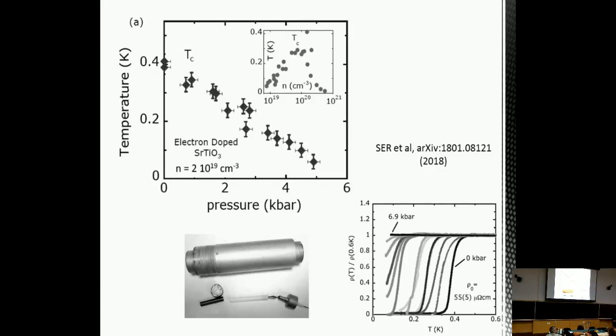And we measured the pressure dependence of superconductivity in strontium titanate. So here's the resistivity versus temperature at different pressures. And you can see here the red curve shows that superconductivity is rapidly destroyed with very small pressures, just a few kilobar, 5 kilobars. So the electron bands and the electron density are hardly changing at all over this range. So how could it be that superconductivity is destroyed so quickly with pressure? And this is just to remind you that there's also a dome of superconductivity as a function of carrier density.